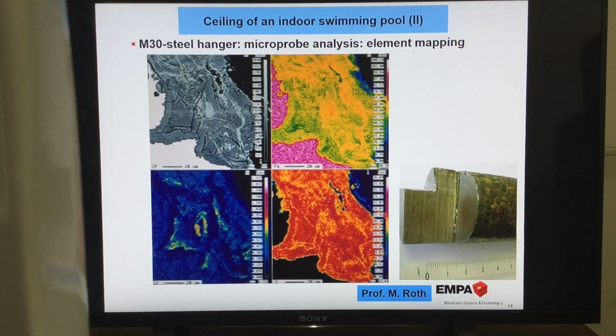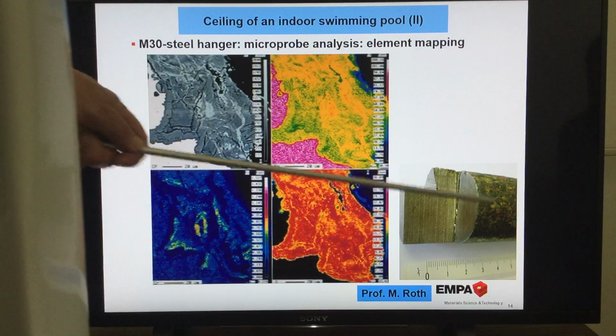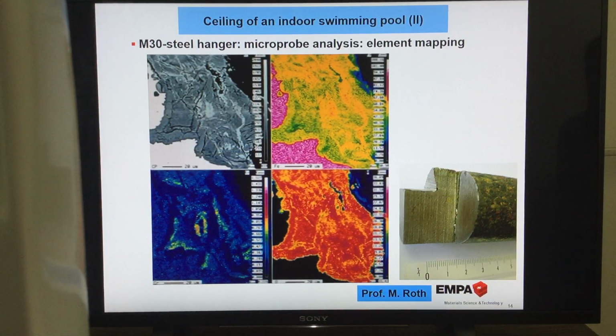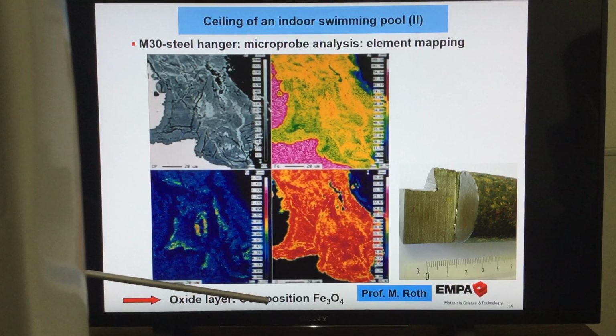However, this just shows you a little bit of overview. For precise measurement, what kind of examination do we take? We scratch away some material from the oxide layer, bring it to the chemical laboratory, and they will tell us exactly what the composition is. And you can already guess what we found. The oxide layer was a composition of Fe3O4.